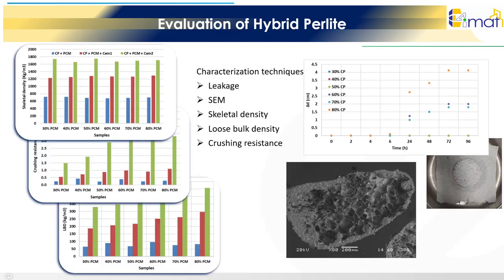The hybrid perlite was thoroughly evaluated to ensure its suitability for mortar applications. The assessment included leakage tests, SEM microscopy, skeletal and loose bulk density measurements, and crushing resistance. These tests allowed us to understand both the stability of the encapsulated PCM and the mechanical robustness of the composite particles. From the examined grades, the optimal product was the one exhibiting minimal PCM leakage, lower density, and higher crushing resistance, ensuring both good thermal performance and sufficient durability during mortar mixing and application.